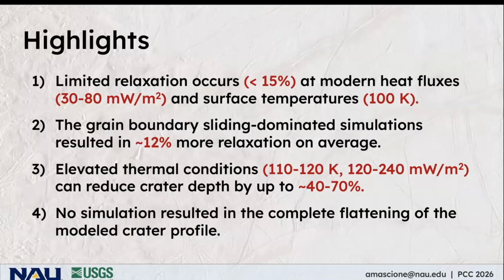So to summarize, we found that limited relaxation occurs under modern heat fluxes and surface temperatures, and it's not until we invoke elevated thermal conditions that we begin to see significant depth reductions. In particular, our grain boundary sliding simulations resulted in about 12% more relaxation on average and reached depth reductions ranging from 40 to 70% relaxation under moderately elevated thermal conditions.